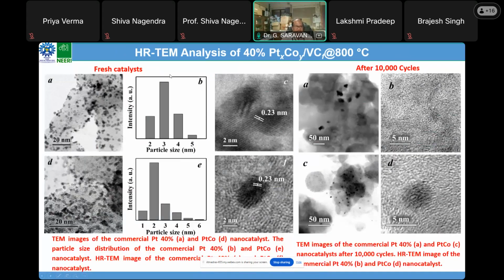The fresh catalyst has a roughly 2 to 3 nanometer size. After 10,000 cycles, the particles get agglomerated. Here also there is some agglomeration, but not as much as in the commercial Johnson-Matthey catalyst. So the PtCo combination is really better for an oxygen reduction catalyst.